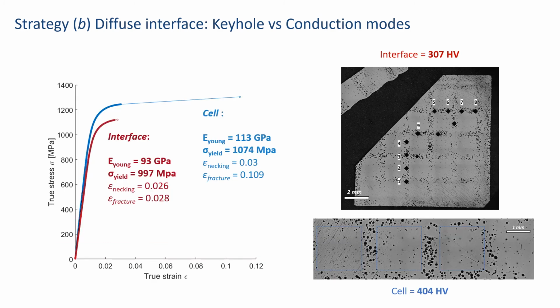So these are the first mechanical results that we have for these architectured materials. On the left, it's actually not architectured materials, but tensile tests printed with the parameters of the cell, so the dense material, or the parameters of the interface, so the porous material. And you see that indeed there is a decrease of the Young's modulus and the yield stress of the material because of the softening effect of the voids. And by using microhardness, we could also see that there is a roughly 100 HV drop in the hardness of the interface as compared to the hardness of the cell. That is in good agreement with the yield stress from the tensile test on the left, and that means that we successfully created a material that contains interfaces with a lower yield stress compared to the cells that have a higher yield stress.